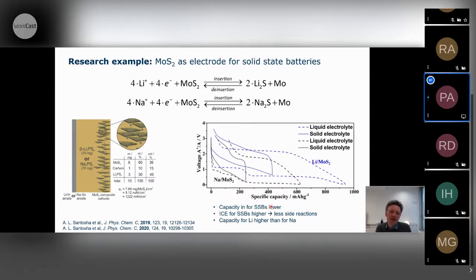And what you can also see is that if you compare lithium and sodium, the capacity in the case of lithium is always a bit higher compared to sodium, very likely because of more sluggish kinetics in the case of sodium. But for sodium, we found that if you go to slightly elevated temperatures, then you can have a much higher capacity. And this is always a good sign because kinetic limitations are something you can try to improve. If it would be a thermodynamic problem, then you usually have not really an option to get an improvement, right? But kinetics is something where, as a chemist or electrochemist, there are ways to tackle it.